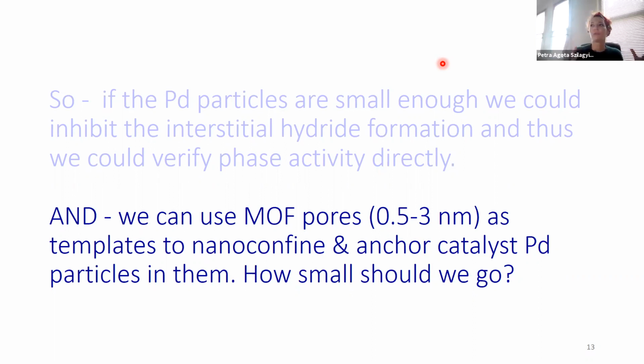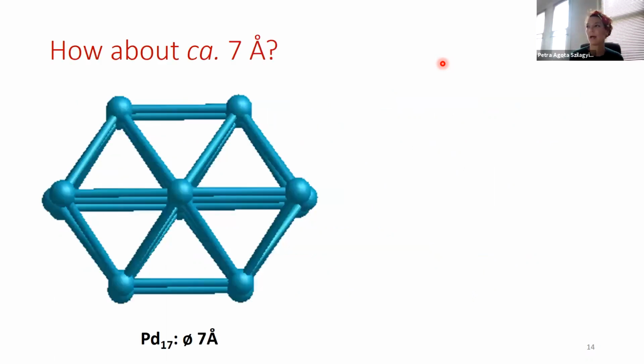And so, of course, what we could do ideally is have all different sizes and see what is the cutoff point where the hydride formation no longer occurs. Now, instead of that, we just went for a relatively safe option. And we went for this palladium 17 cluster that I've already shown you. And what I would like you to note here is that this is constructed so that there is one palladium atom in the middle and the rest are all surface atoms.